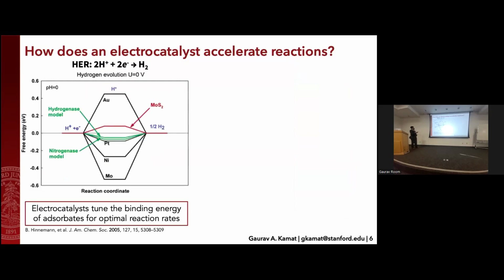Well, here's an example of a hydrogen evolution reaction. Green hydrogen production is based on this reaction. If you start from protons and you make hydrogen as your goal, it turns out that doing that reaction in a vacuum is very, very energetically intensive. A catalyst will enable this to go faster by creating an intermediate state, usually on a surface. And once it's on that surface, depending on the binding energy of that metal for the certain adsorbate of that reaction, you can enable a much, much faster reaction.